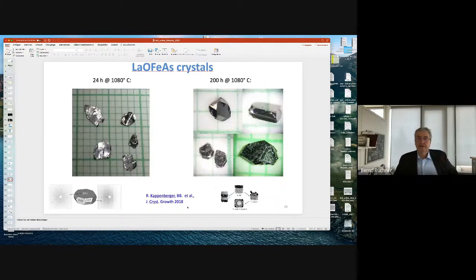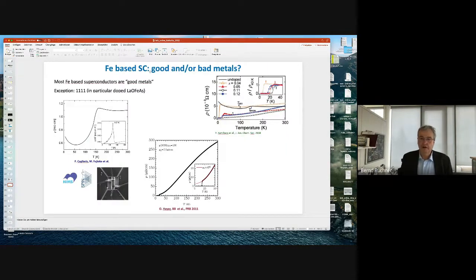And this is, okay, the starting point for going back to these crystals. So that was a couple of years back. We found a possibility. It's a complicated process. It's a solid state growth process, which is depicted here, which then leads to these nice faceted crystals. So the first time now we could use this material there. We have this splitting, as I've shown you, between these two transitions, different from the other systems. So it's where we have two instabilities, and we can use this material to have a closer look on this nematic order.